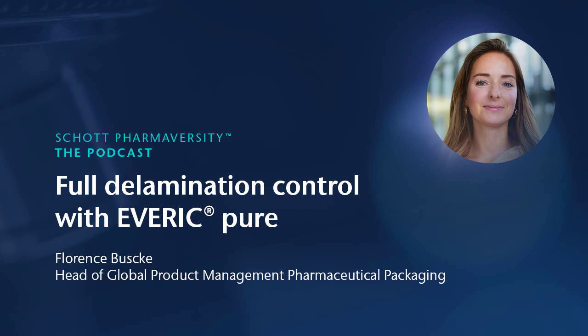Those delamination flakes in glass containers have become a serious quality concern in, let me say, the last 10 years. It's not that they were not known before, it's just that recalls have caused serious attention. And it's that serious because glass delamination typically occurs weeks or months after filling. So you cannot see it right after filling, you cannot inspect it. And as I indicated, there are a lot of factors that contribute to that.